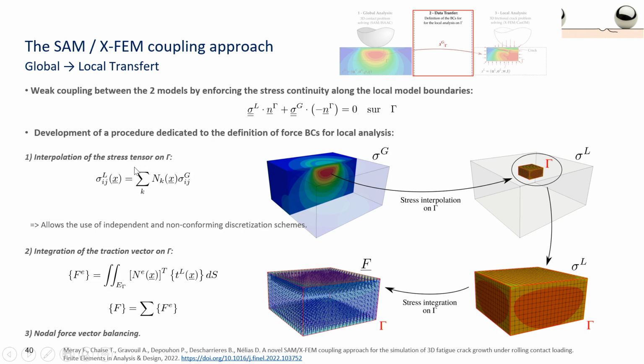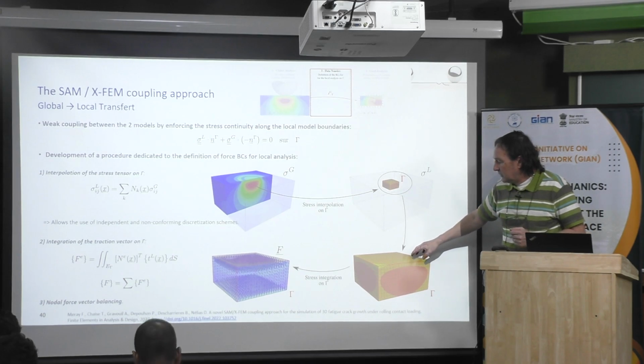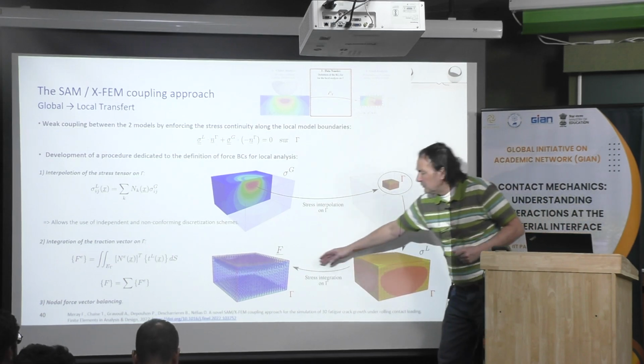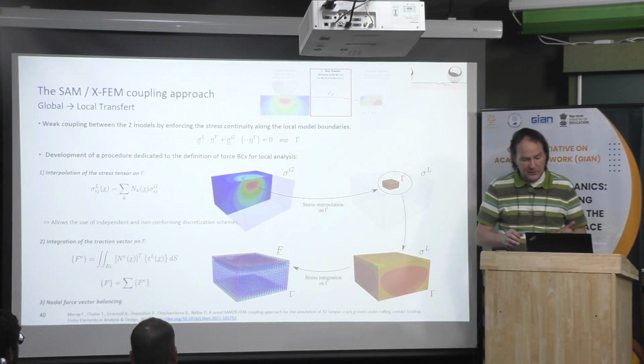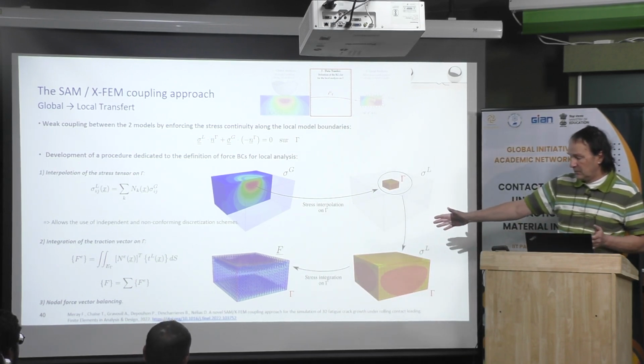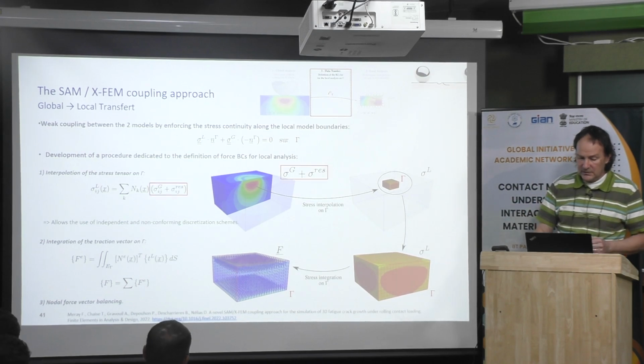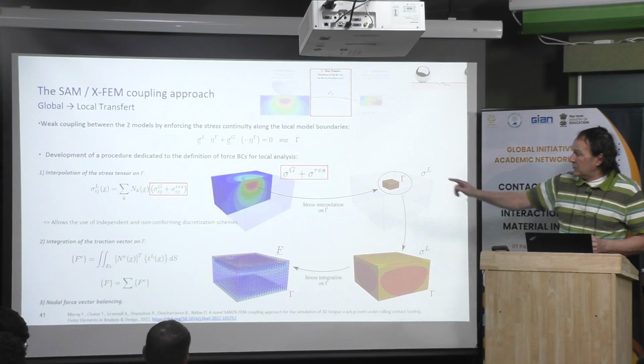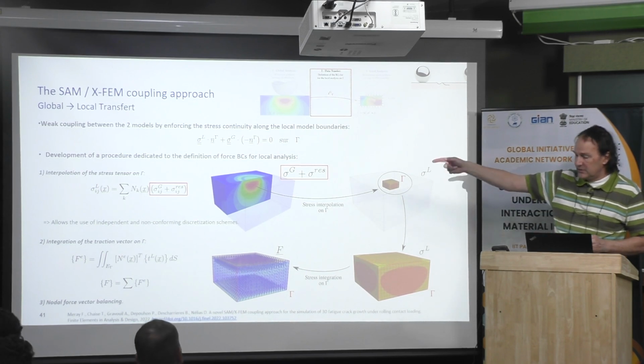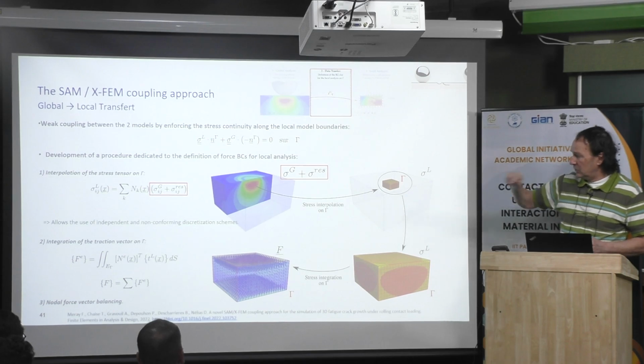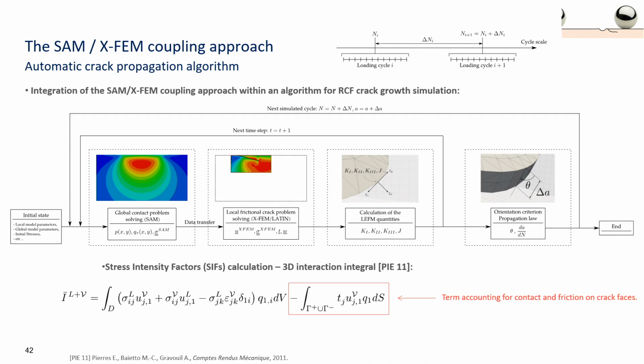Then the idea is to calculate the stresses on each surface of the element. We interpolate the stress, and after we apply the boundary conditions to the box, and then in the box now we have the crack. Then the geometry is very simple. It's just a square box with a crack. We may also use residual stresses. We just have to add these stresses in the resolution, and of course we may have a gradient of residual stresses, or you can have residual stresses from the denting.